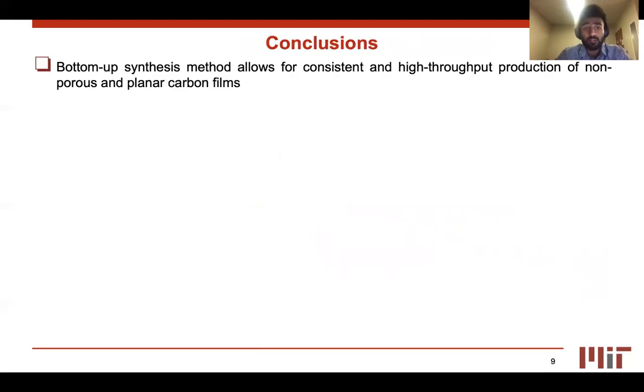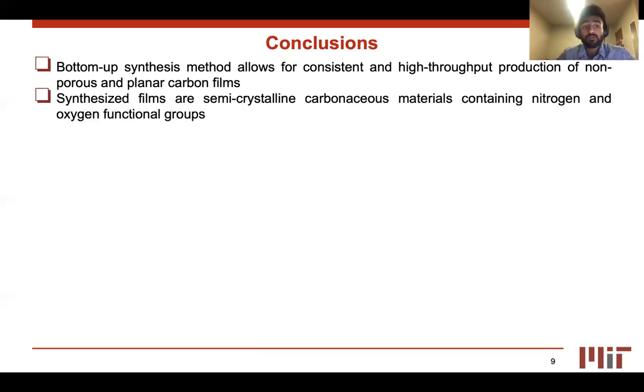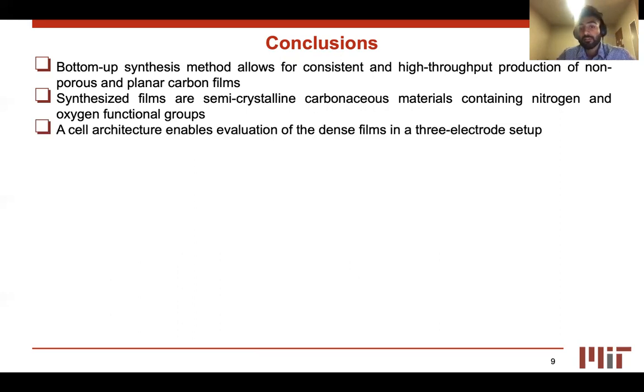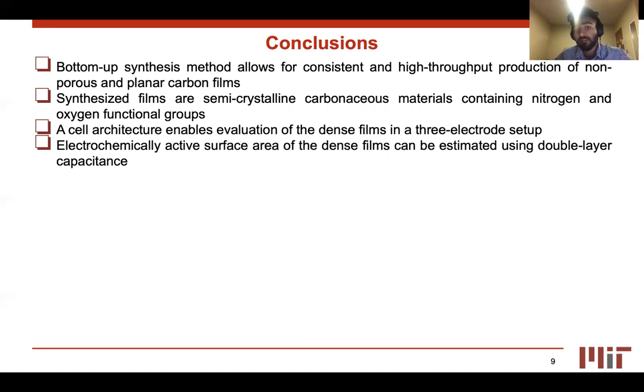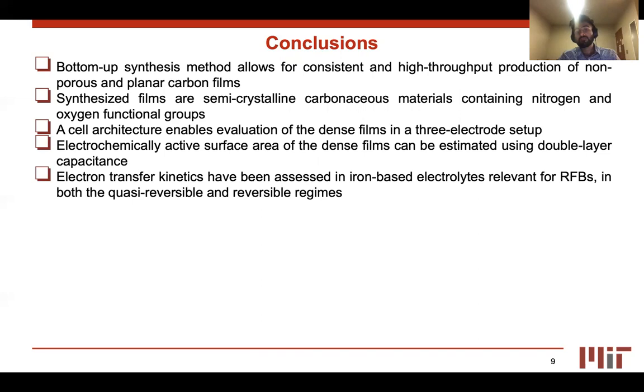In conclusion, the bottom-up synthesis method allows for consistent and high throughput production of the non-porous and planar carbon films. We also can say that the synthesized films are semi-crystalline, carbonaceous materials containing nitrogen and oxygen functional groups as seen with the suite of spectroscopy. A cell architecture enables evaluation of the dense films in the three electrode setup as the traditional voltammetric techniques were applied. Electrochemically active surface area of the dense films can be estimated using double layer capacitance. And finally, the electron transfer kinetics have been assessed in iron-based electrolytes as shown, relevant for RFBs in both the quasi-reversible and reversible regimes.